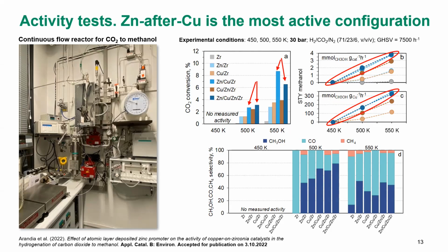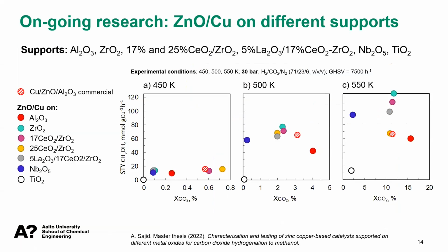And if we look at the methanol production, we also see that the blue dots corresponding to zinc, copper, zirconia, and zinc, copper, zinc, zirconia, they yielded higher methanol production rates. So this is interesting. And then something that we have been working with in the last months is somehow related to the same thing, but with different supports. So we selected that the zinc oxide after copper was, let's say, the configuration with the best potential. So we decided to follow the same preparation method, but on different supports.